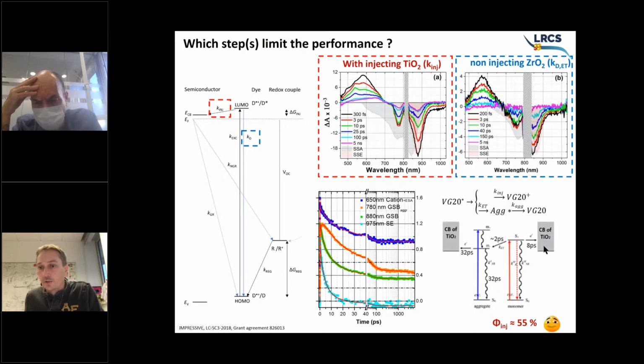And the injection from the monomer is in 8 picoseconds. It means that it is faster to energy transfer to the aggregates than to inject into titania. And then from the aggregates, you can inject into titania, but in 32 picoseconds. If you calculate the total injection yield of the system, one will find that injection is a 55% yield. And this is in very good consistency with the IPCE, which was showing a maximum of 60%. You cannot go above 55, 60% IPCE with that low injection yield.